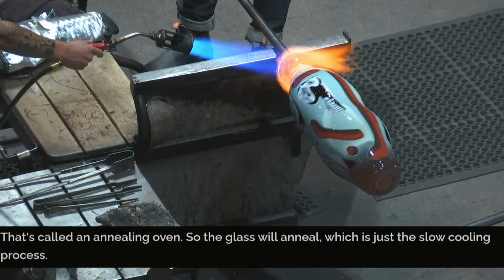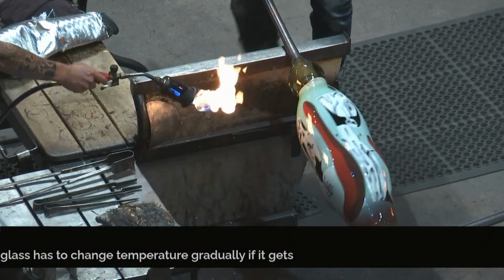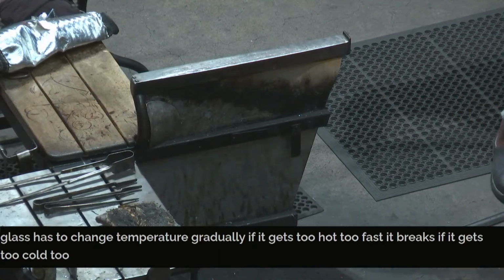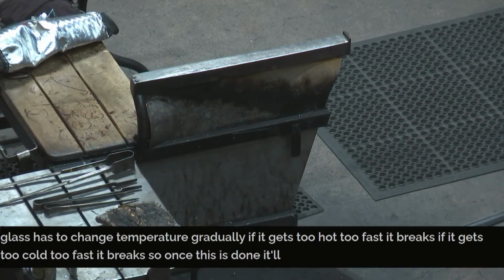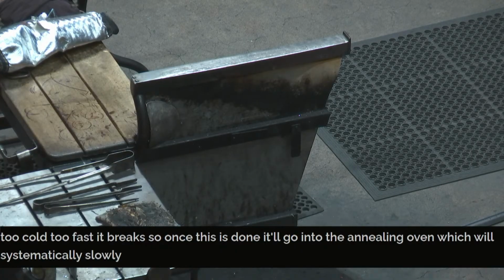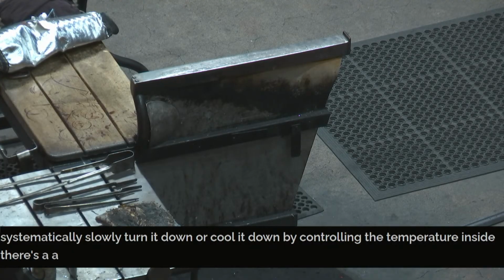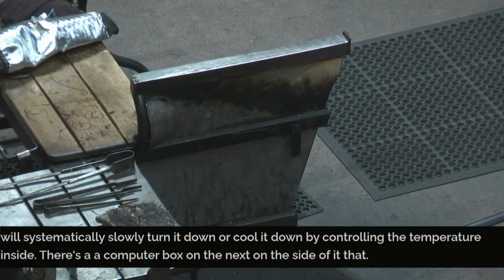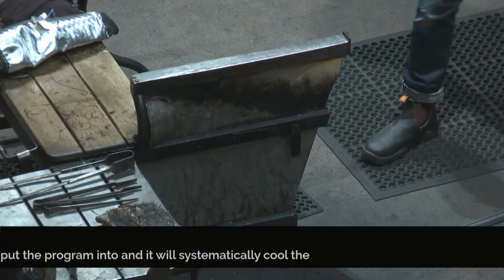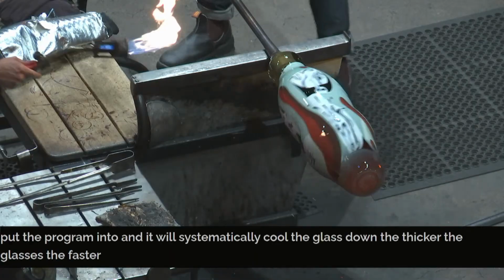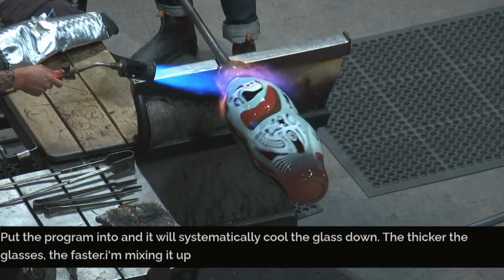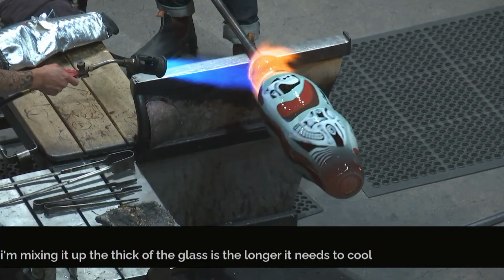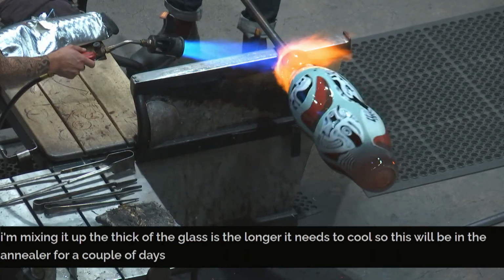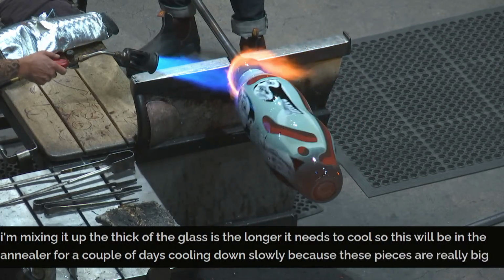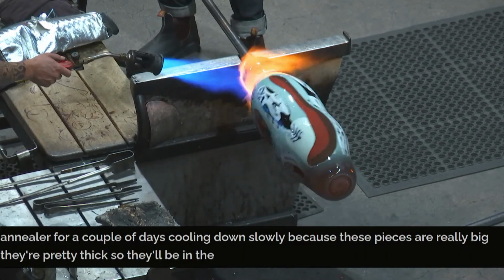Glass has to change temperature gradually. If it gets too hot too fast, it breaks. If it gets too cold too fast, it breaks. So once this is done, it'll go into the annealing oven, which will systematically slowly cool it down by controlling the temperature inside. There's a computer box on the side of it that you put the program into, and it will systematically cool the glass down. The thicker the glass is, the longer it needs to cool. So this will be in the annealer for a couple of days, cooling down slowly, because these pieces are really big, they're pretty thick, so they'll be in the annealer for a while.